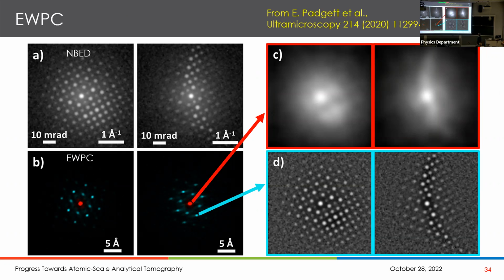At any rate, I won't go into a huge amount of detail here, but this is the exit wave power cepstrum. These are the nano beam electron diffraction patterns. So that's reciprocal space. Down below is back to real space. All right, those are atom positions. But down here you can separate that and look at, if you go back to reciprocal space from just that information, you see that it is correlating roughly with the large spatial or reciprocal space frequencies, and also here. At any rate, what we're more interested in is the atom positions away from that center. And so what you see is a very high quality rendering of the spatial frequencies recovered in real space.